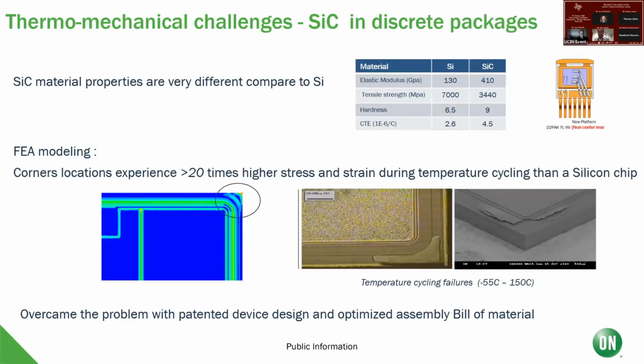Next slide. One of the key things when you think about packaging, and that really stares hard at you, is the mechanical aspect of it. So thermal-mechanical, in addition to the electrical, are the threefold packaging challenge now with these wide bandgap, high power density kind of devices. On the top, you see a quick summary of how different silicon carbide is in modulus, in tensile strength, in hardness, and so forth than silicon. Those are the mechanical properties, but on a package level, they matter. Things break at corners. They always do, but even more so in silicon carbide. So we need different ways to deal with the die size stresses during fabrication and during temp cycling.